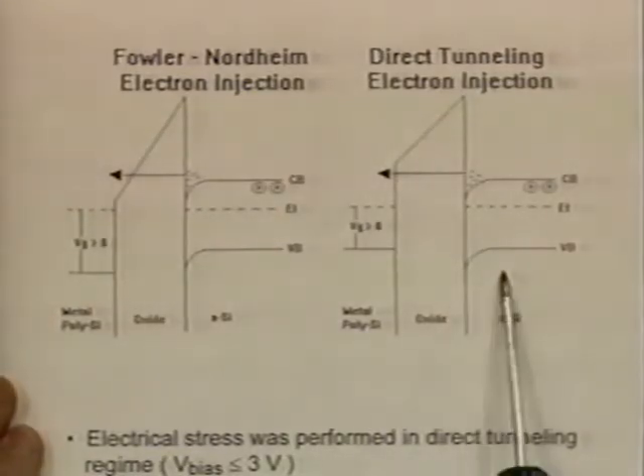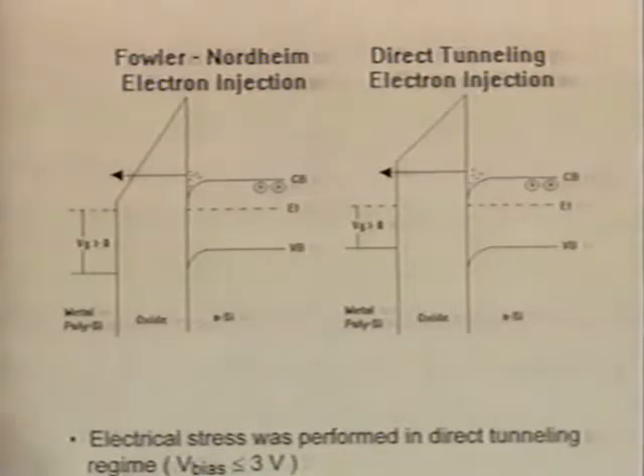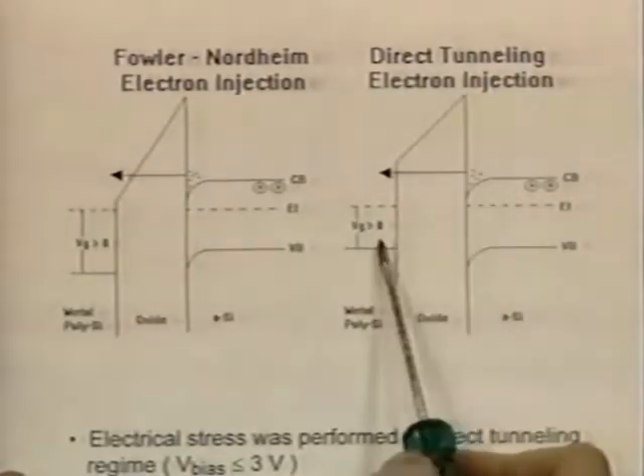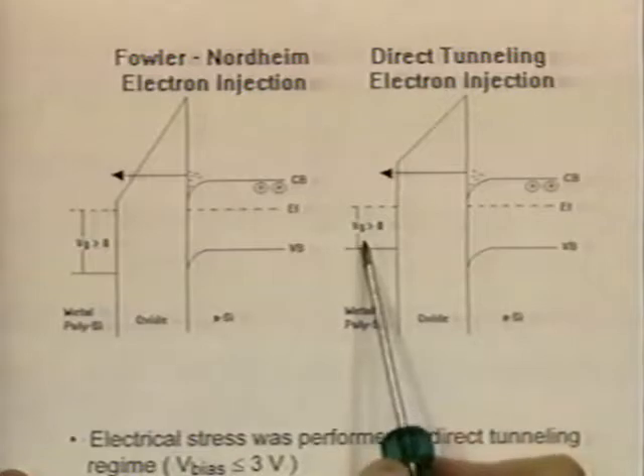And so I think holes are important, not energy of the electrons, because otherwise I'm not sure how I can explain these thresholds. If it's energy of the electrons, in one case, the energy of the electrons is this from here to here, about 1 electron volt. In the other case, the threshold says that the energy has to be about 2 electron volts. And I can't see why you have a 1 electron volt energy threshold in one case and a 2 electron volt energy in the other case.